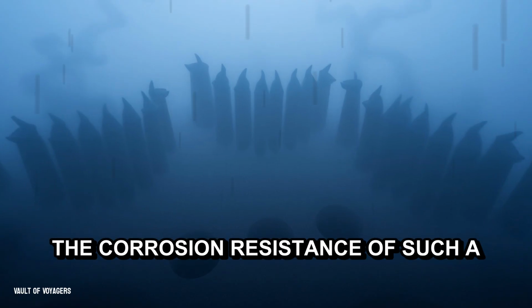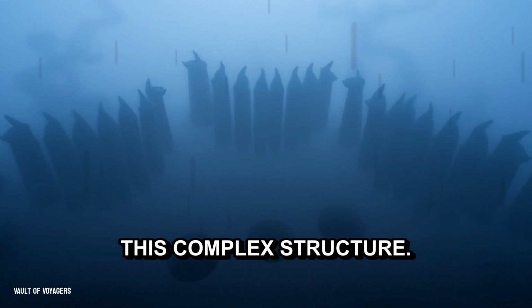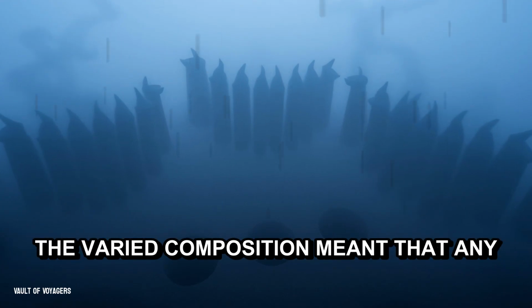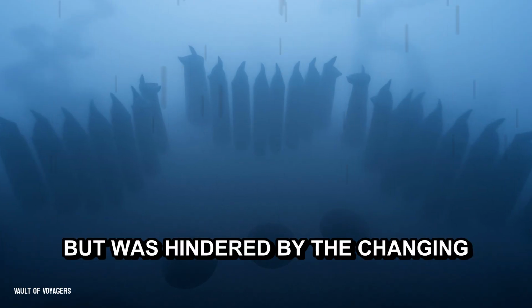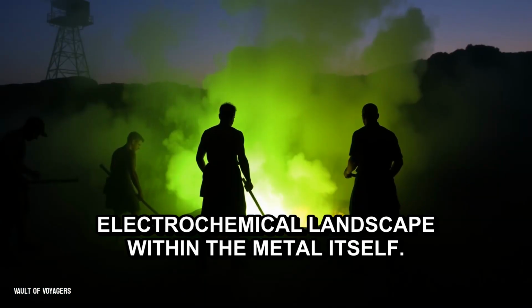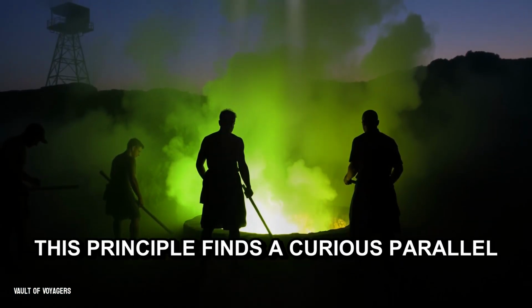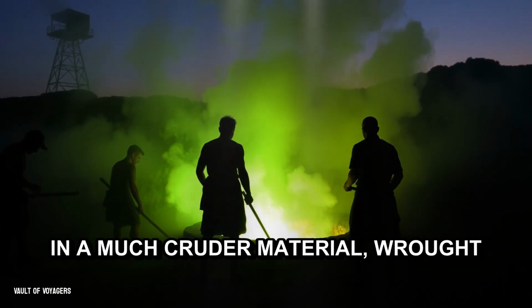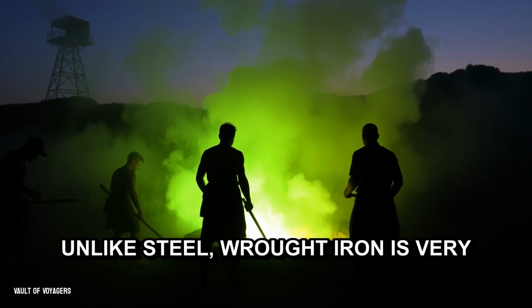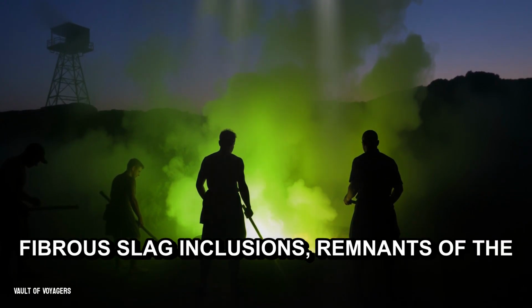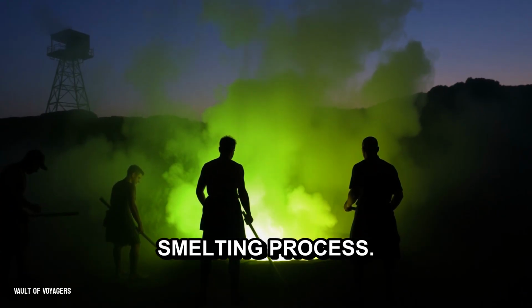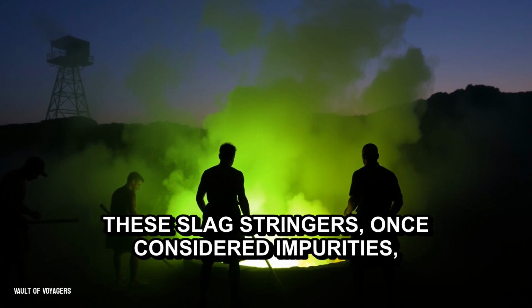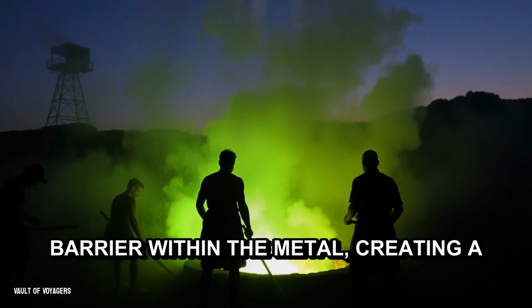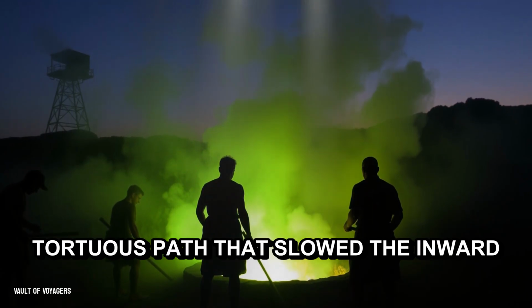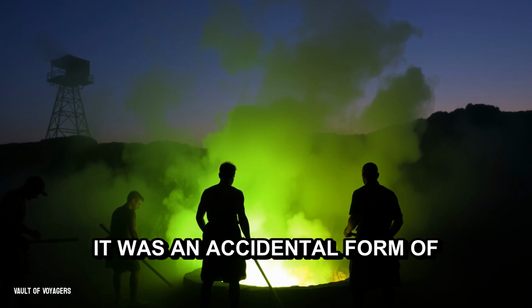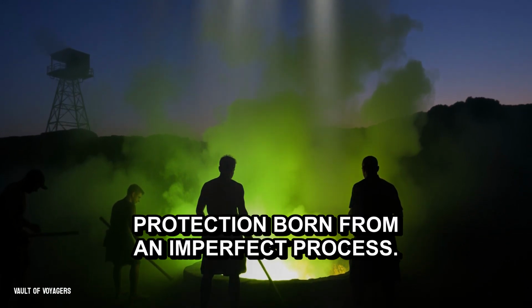The corrosion resistance of such a blade was an indirect benefit of this complex structure. The varied composition meant that any corrosive attack did not spread evenly, but was hindered by the changing electrochemical landscape within the metal itself. This principle finds a curious parallel in a much cruder material, wrought iron. Unlike steel, wrought iron is very low in carbon, but contains long, fibrous slag inclusions, remnants of the smelting process. These slag stringers, once considered impurities, could sometimes act as a physical barrier within the metal, creating a tortuous path that slowed the inward progress of corrosive agents. It was an accidental form of protection born from an imperfect process.